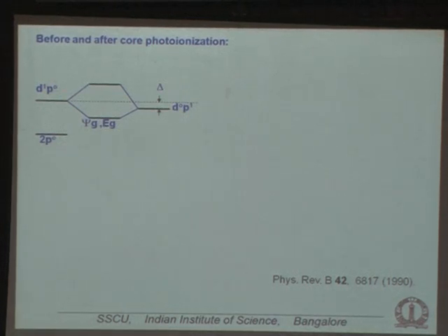But remember the hopping we talked about. This hole can hop back and forth with oxygen, which is the same as the electron hopping back and forth. If this hole hops to the oxygen side, I'll have 1 hole in the oxygen and no hole in the copper. The energy difference between this level and that level is exactly the charge transfer energy that I've already defined for you earlier. And this hopping strength, if it is T, then I get a bonding and an antibonding. This splitting is given by essentially twice T. It's also dependent on a little bit of delta.